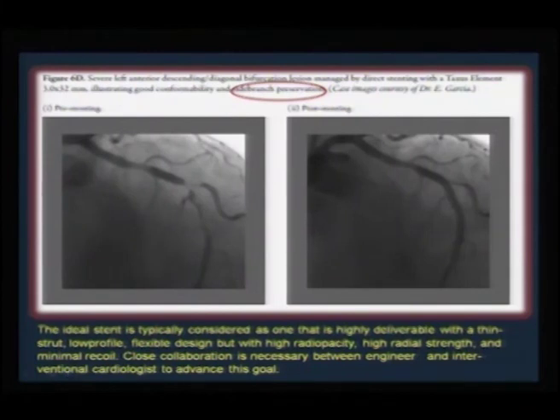And similarly a side branch is preserved. In this case you can see the blockage is here, and very carefully, because this side branching is very intricate. So if you are going to employ it, you should not rupture this branch, and you can see using Taxus Element, which is nothing but your platinum chromium alloy, you can do the side branch preservation. The ideal stent is therefore typically considered to be highly deliverable with a thin strut, low profile, flexible design, and radiopacity.